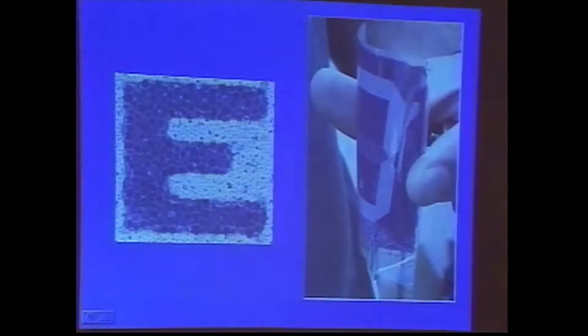The external capsule, typically the smallest capsule that we create here is about 10 microns or so. The internal nanoparticles are about 100 nanometers depending on which color we're interested in. It's really the electric field that defines the image as opposed to these capsules. In most recent chemistries, these capsules actually close-pack and self-assemble into close-packed arrays.